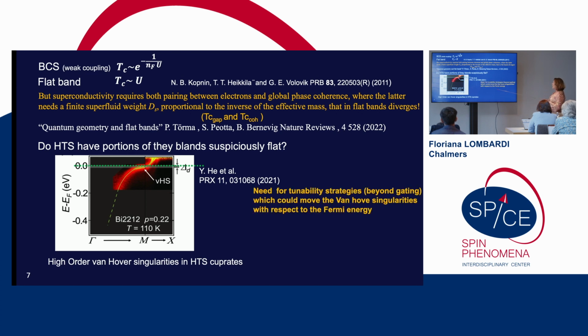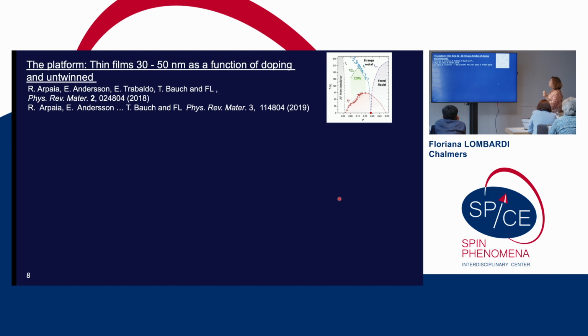But what we want to do now is tune this van Hove singularity in our films and see how the properties are changing by changing the position with respect to the Fermi energy. And this is the substrate engineering that I was telling before. Okay, so the first thing that you need is to establish a platform of thin films as a function of doping that, when they are thick, reproduce the same properties of the single crystal, so you have the same phase diagram. And then you need to have them untwinned. You remember that oxygens are in the chains, so you need to have chains that are preserved on the substrate.